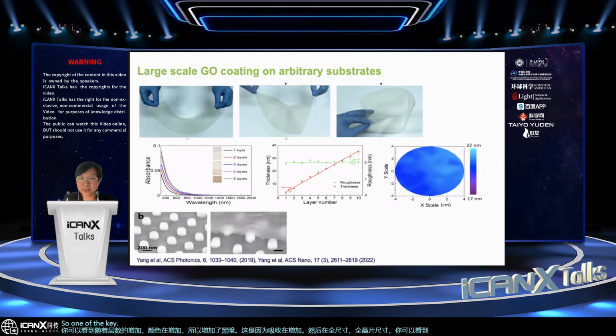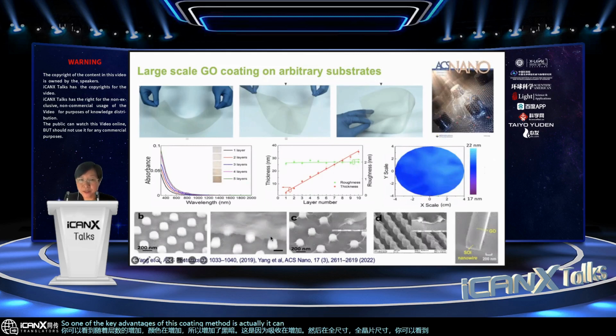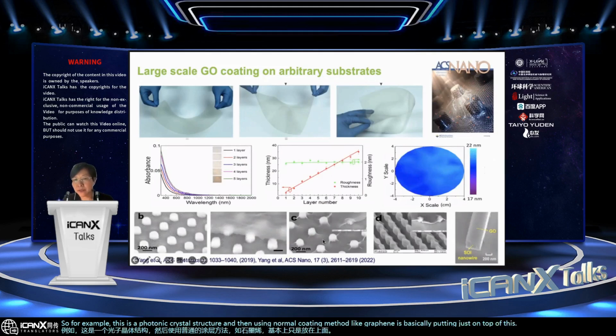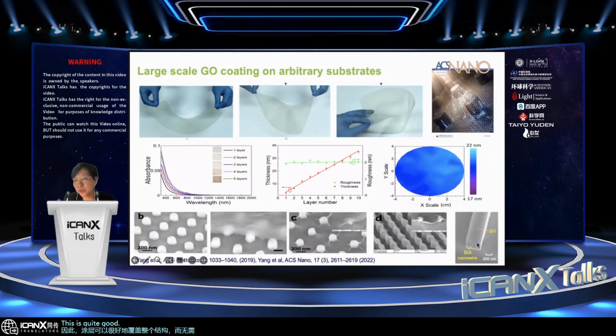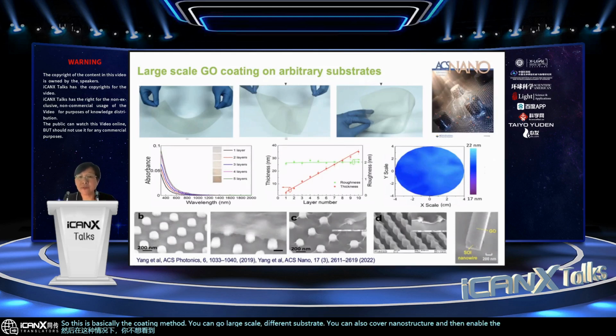One of the key advantages of this coating method is that it can coat nanostructures. For example, this is a photonic crystal structure, and using a normal coating method, graphene is basically just put on top of the structure. But using our coating method, you can achieve what we call conformal coating. The coating can very nicely cover the entire structure without any gap. This is quite critical when you talk about optical devices, because you want very nice coupling between the waveguide, for example, and the 2D material. In this case, you don't want to see any gap. So this is basically the coating method. You can go large scale, use different substrates, and also cover nanostructures, and then enable the functionality in different devices.